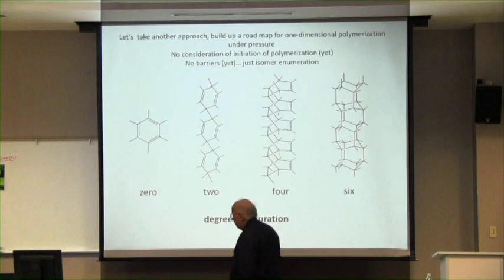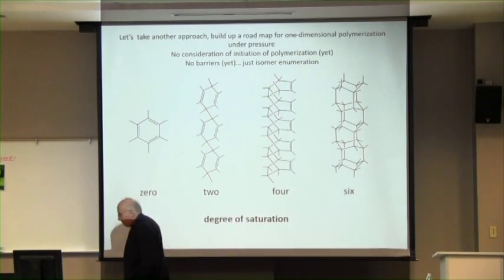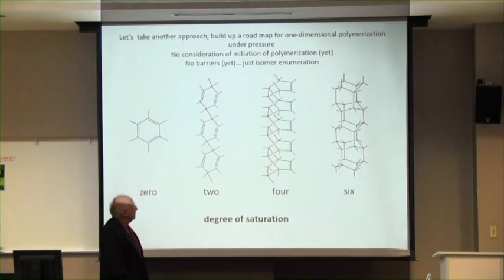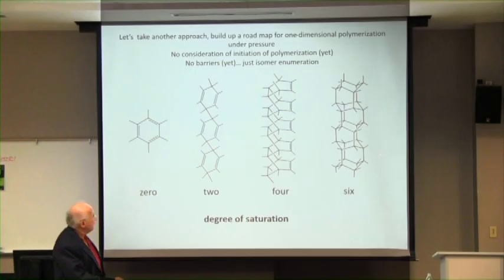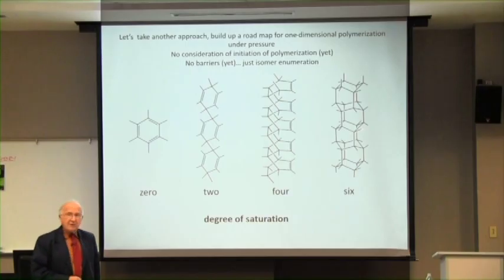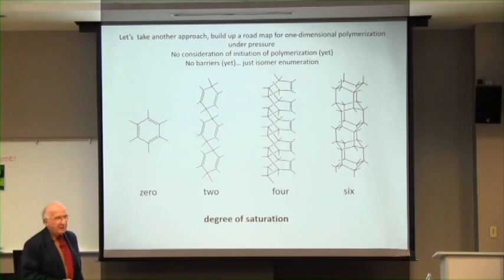Anyway, what we thought we would do, Bu Chen and I, and joined by these other people, is to try to provide a roadmap for the polymerization. The Penn State people had enumerated these. We thought that along the way there surely must be polymers with, it's not all going to happen in one fell swoop. You can be sure about that. And even this is naive because the polymerization, no doubt, is nucleated. It starts out at some radical site that's being formed.